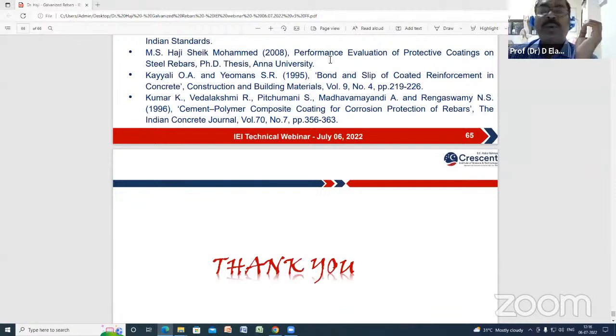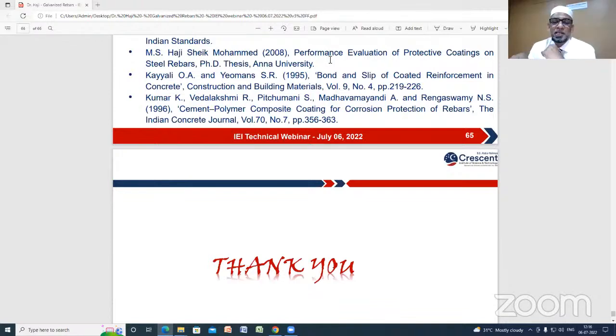Mr. Babu is asking whether there will be any reduction in bond strength. I have given an answer in the presentation. No reduction in bond strength. You will get almost similar bond strength compared to conventional rebars. Since it is a metallic coating, the thickness is only 50 to 75 microns, so it won't hinder bond strength. And scientifically, many researchers have reported there is no reduction.